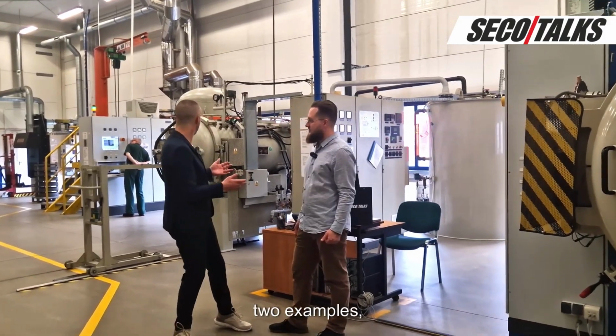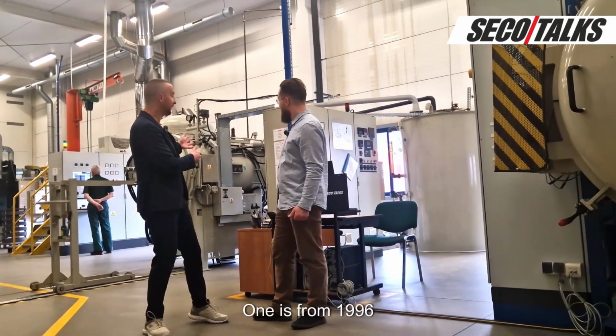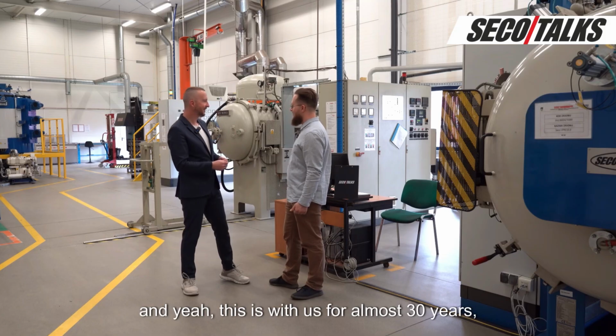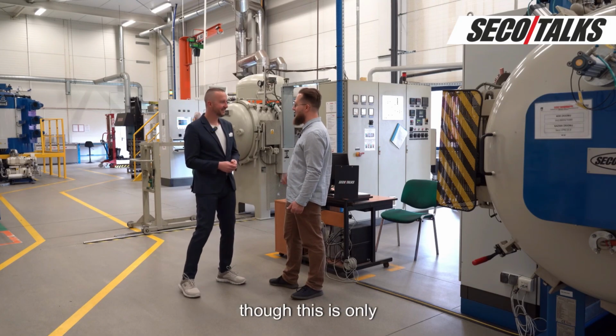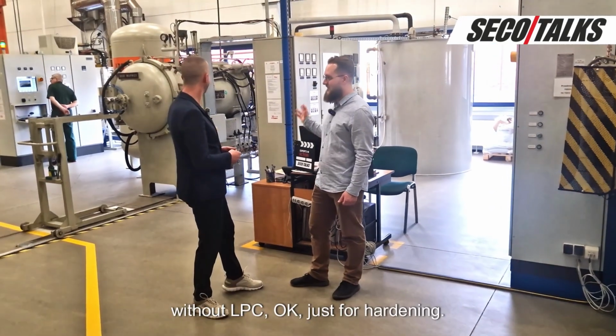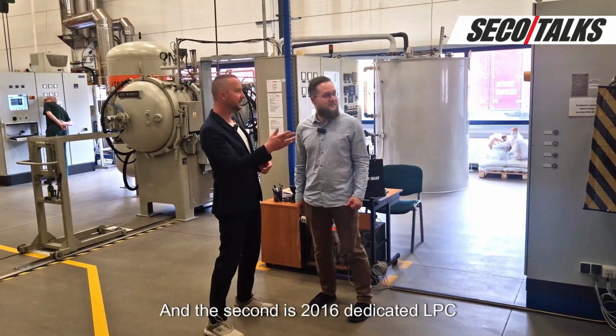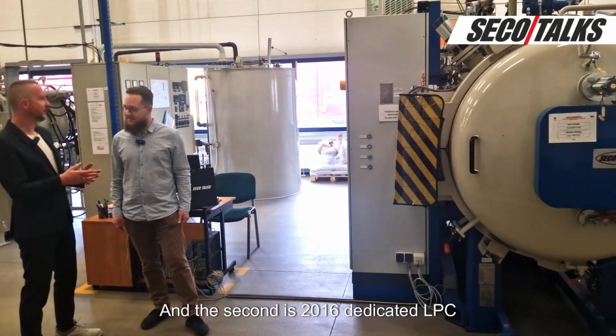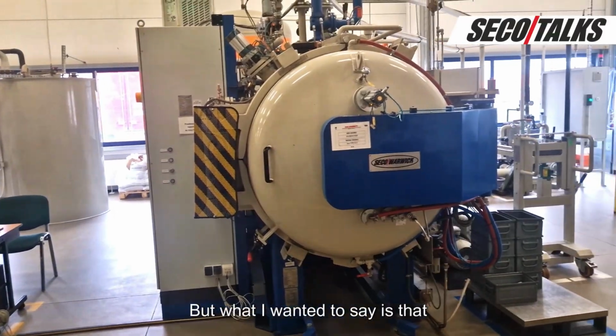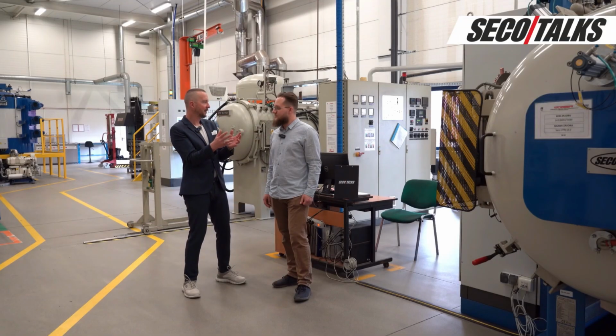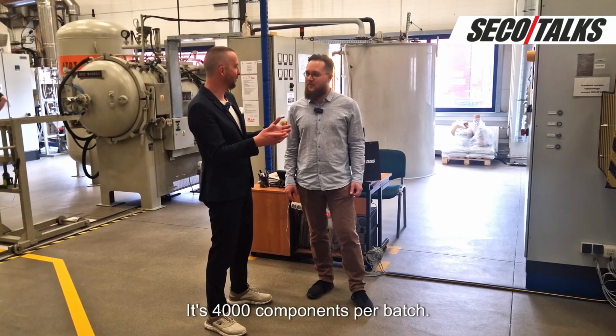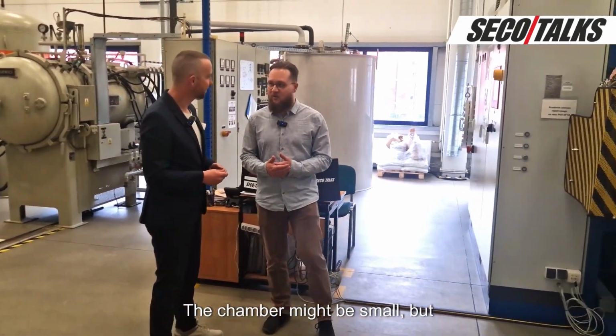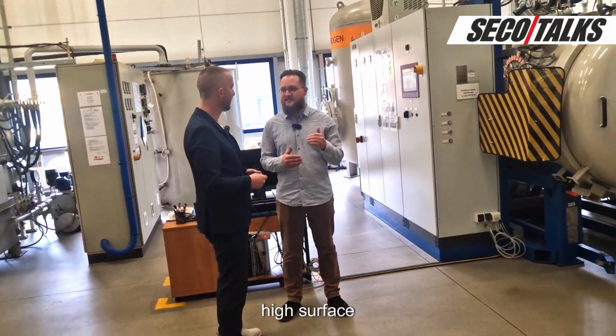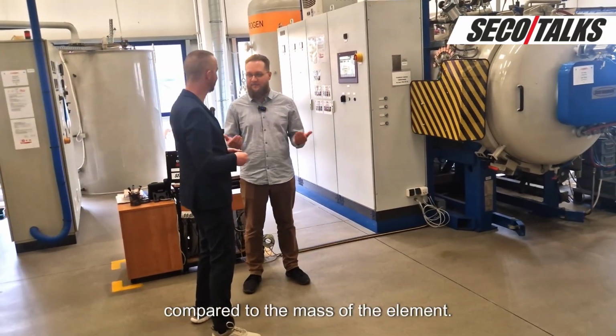We have two examples. One is from 1996, and this is with us for almost 30 years. This is only gas quenching without LPC, just for hardening. And the second is 2016, dedicated to LPC process. But what I wanted to say is that it's a relatively small chamber, a small industrial furnace, but very efficient. It's 4,000 components per batch. The chamber might be small, but our elements have a very high surface compared to the mass of the element.